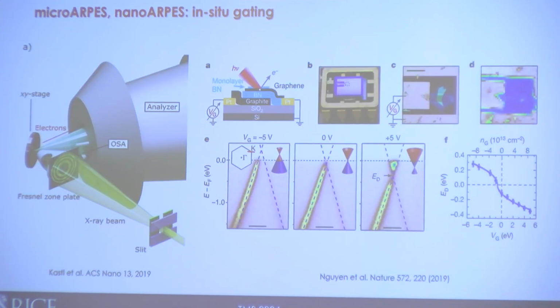So for micro ARPES and nano ARPES, there's been development. This is work from Eli Rotenberg's group at the Maestro Beamline. This is the nose cone of the electron analyzer; the hemisphere is back there. But basically, they can manage to focus the beam down to a micron. Micro ARPES is usually something like a 10 micron beam spot, and nano ARPES is sub-micron, so now maybe 100 nanometer spatial resolution.